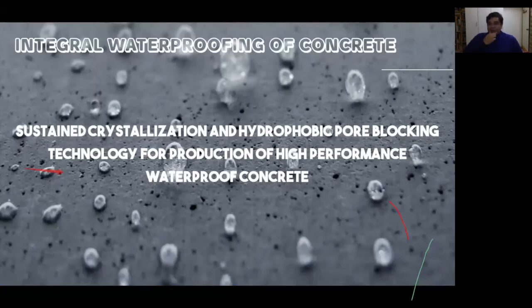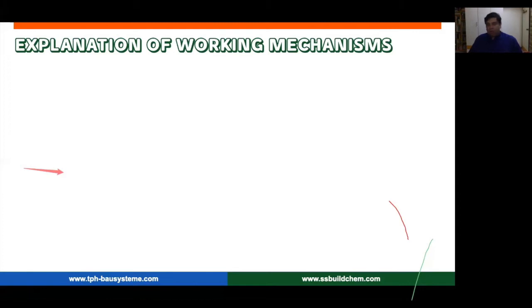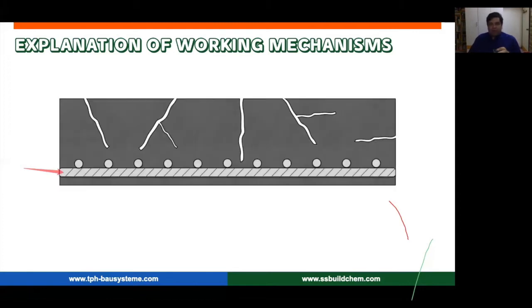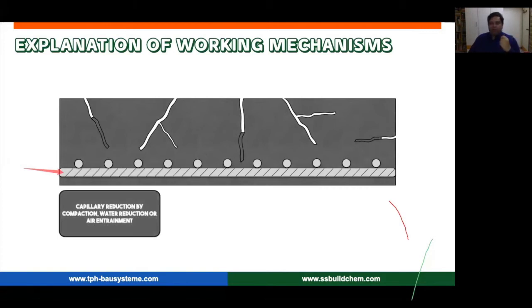So, once we began thinking about how to improve concrete, we thought about using sustained crystallization systems or hydrophobic pore blocking technology, and we can use this to prevent water coming through your concrete. To give you an idea of the working mechanisms, if you're using the right type of integral waterproofing additive, part of it will work by reducing your capillaries in your concrete itself. That means your mix becomes easier to compact. It helps a little bit with water reduction. Maybe in some cases it also entrains a little bit of air. But once all these things come through, it helps your capillaries themselves to reduce over time.